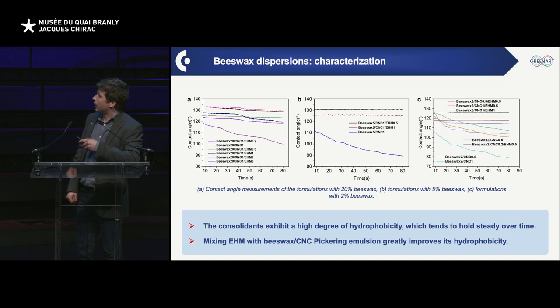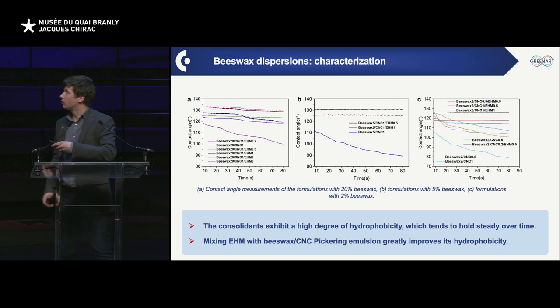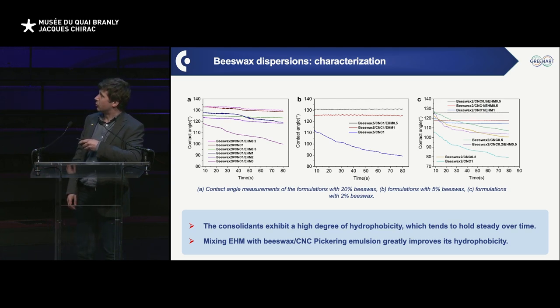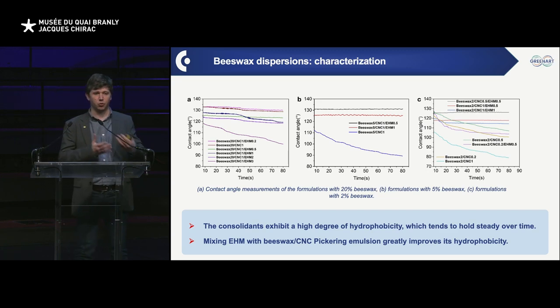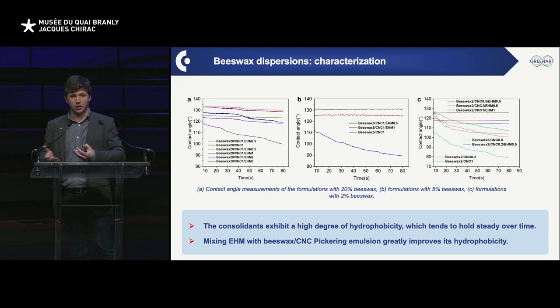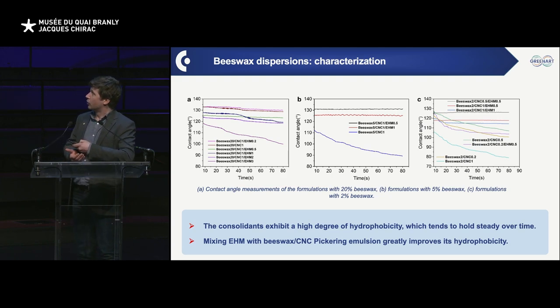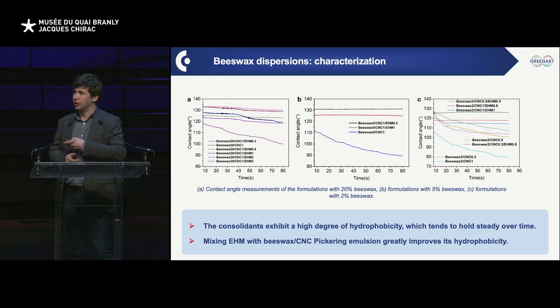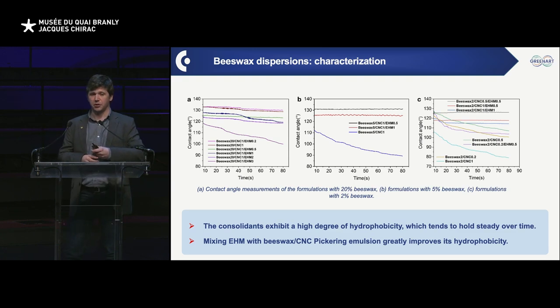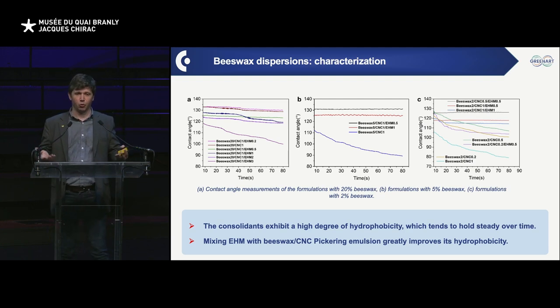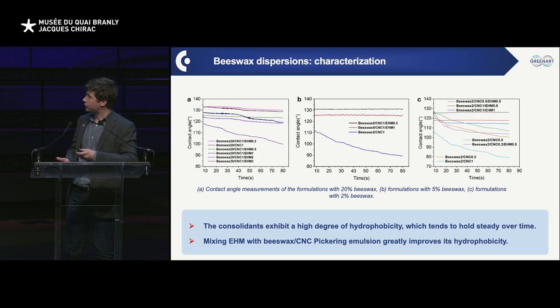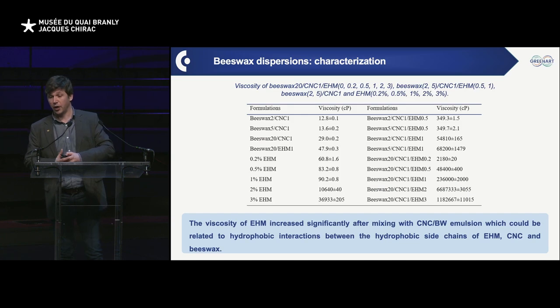We can see that if we only have the emulsion that is still beeswax based, well, it has a good hydrophobicity, but rapidly the contact angle decreases. So that means water gets uptaken by the system. Even though it is beeswax, because there is a lot of nanocellulose, it's still hydrophilic per se. Now, when we start to mix that with the hydrophobically modified cellulose derivative, we boost significantly the hydrophobicity, and more importantly, it remains very stable over time. So that means if we have this formulation, we apply it on a substrate, it is supposed to withstand water exposure for quite a lot of time. So that was a bit unexpected, and we're very happy with it.